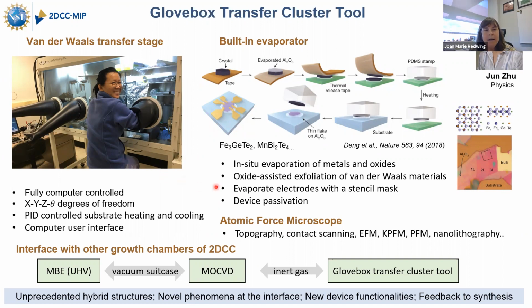And it will also have a built-in evaporator for the deposition of metals and oxides. And that's needed to exfoliate certain crystals that have stronger van der Waals bonds. Also, you can use the evaporation to passivate surfaces or to deposit electrodes using a shadow mask.